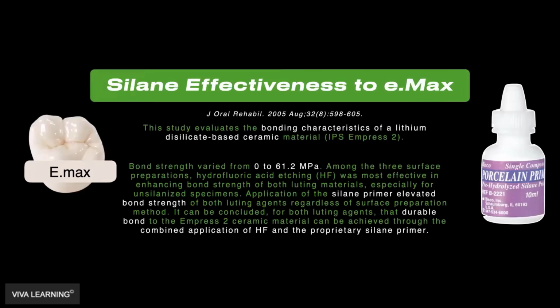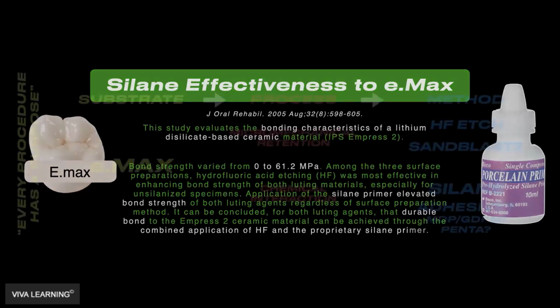Now, again, do you have to use silane? Basically, they've found, this is my favorite part of the study, bond strength varied from 0 to 61 megapascals. 0, I love that. Basically, if there is some saliva introduced or anything that could negatively impact it, we want to try to use silane. They found that hydrofluoric acid etch with the silane created a durable bond. That is just over and over what they found.